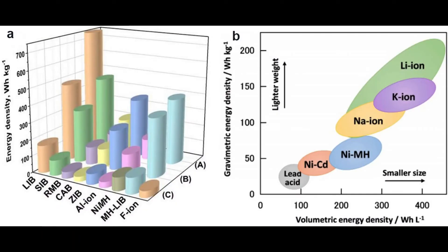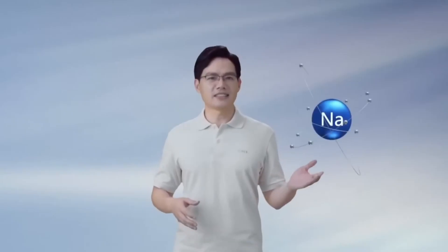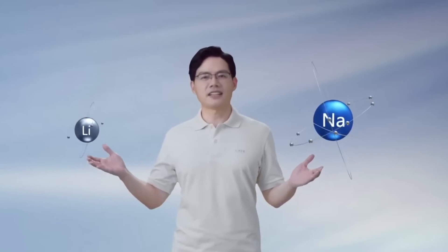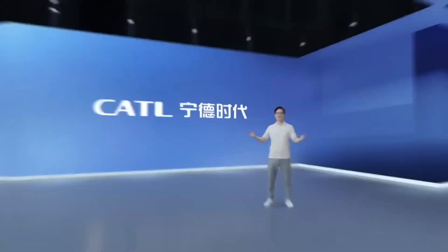Of course, no technology is perfect. Sodium ion batteries have lower energy density, because sodium ions are heavier but still carry only one charge. They also have slightly lower round-trip efficiency, about 95% compared to 98% plus for lithium ion. And while CATL claims 10,000 plus cycle life, long-term real-world performance is still being validated.